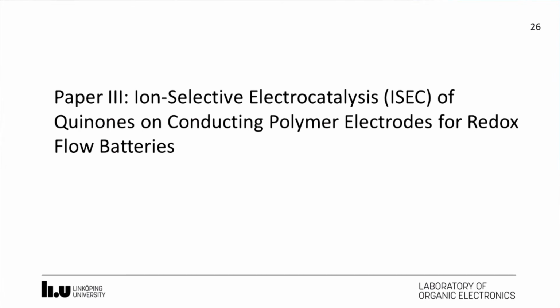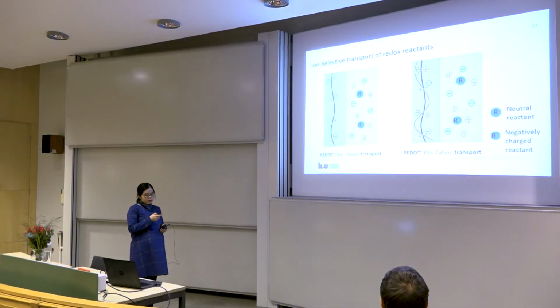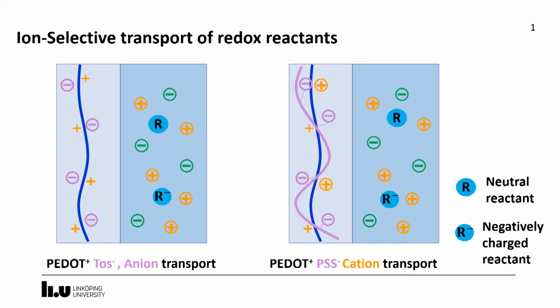The ion exchange mechanism also inspired us to study more about the effect of this on reactants at conducting polymers, for example, charged reactants and their potential applications. Due to the mobility of the counter ion, it's reasonable to assume that neutral reactants will have no effect. So a neutral reactant will have similar access into the bulk of the polymer, and the reaction will not be affected. But for a charged reactant, for example, a negatively charged reactant, it will be much easier to go inside P-dot TOS polymers due to the anion transport, but much more difficult to go into P-dot PSS polymers, and so on. The redox reactions of this reactant will also be affected.